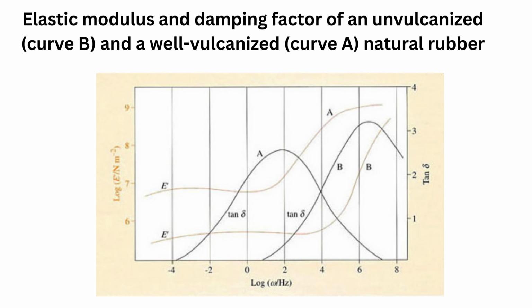The damping factor is then small, but it increases to a maximum value in the leathery transition region between the glassy modulus and the usual low modulus, which is characteristic of rubbers that are deformed slowly. Omega less than 1 cycle per second, or hertz. It is important to note that decreasing the frequency of oscillation imposed on the material is equivalent to increasing the temperature. Glass-like behavior is experienced at high frequencies.